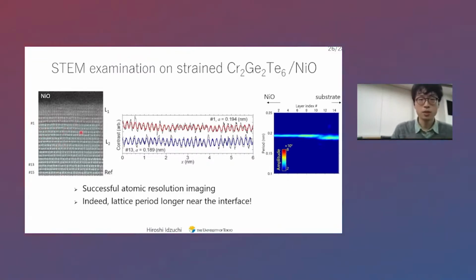place, although it's a small change, we just see contrast as a function of the position, and see some oscillation fit as a function of position. And then it actually indicates a larger lattice constant near the interface with nickel. And by Fourier transform, we actually see more clear behavior. So near nickel, somehow the lattice is a little bit stretched.